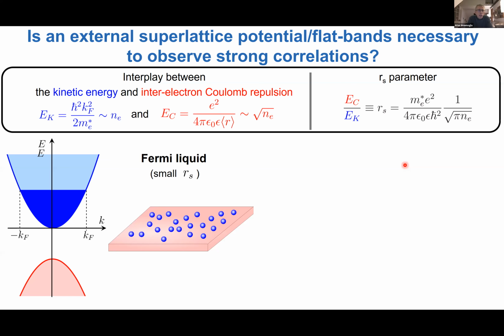And to judge that, let's recall that what is really important in determining whether correlation effects that arise from interactions are important is the comparison between the characteristic energy scale of kinetic energy and the characteristic interaction energy scale. So basically the kinetic energy's characteristic scale is the Fermi energy. This scales in 2D with the density, and then the Coulomb interaction scales as 1 over the distance, and therefore they scale or increase with the square root of the electron density.